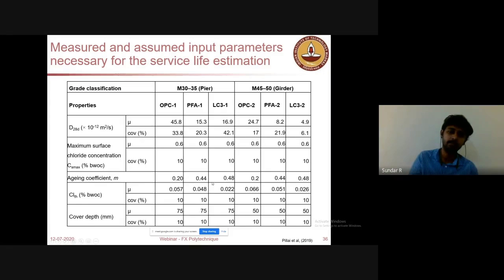And this is the aging coefficient. With respect to time, there are changes inside the concrete in the pore structure, and that is considered with this aging coefficient, which consistently changes the diffusion coefficient with respect to time. This is at 28 days, and the aging coefficient will change the diffusion coefficient from 1 to 50 years or 100 years, whatever we want to calculate. And the chloride threshold will be a constant value.